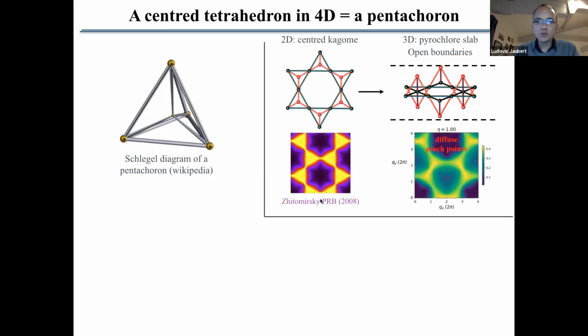This has been known for a long time, and this is a figure from Zhitomirsky from 2008. On the Kagome lattice you have sharp pinch points. But if you do simulations of this 3D pyrochlore slab, with the Kagome and this additional spin up there and down there, these pinch points become broad and diffuse. That's because, even though you still have the Heisenberg antiferromagnetic physics of the Kagome, these spins are not connected to another tetrahedron above or below, so the magnetization flux I was talking about can go out of the system and re-enter somewhere else.